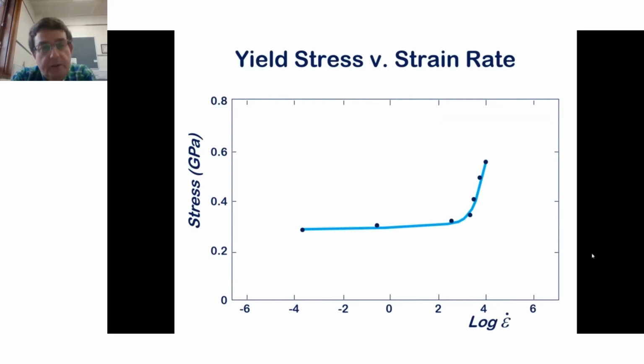Number one, inertia. Inertia becomes important. Inertia acts to maintain the material in its shape. So inertia has the effect of apparently increasing the strength of the material. But also there is another more profound thing occurring, which is when things break, they tend to break via low energy mechanisms. Low energy mechanisms generally take a long time to occur. But if you're hitting something really quickly and you're putting a lot of energy into a system, you are accessing higher energy, faster occurring failure processes.